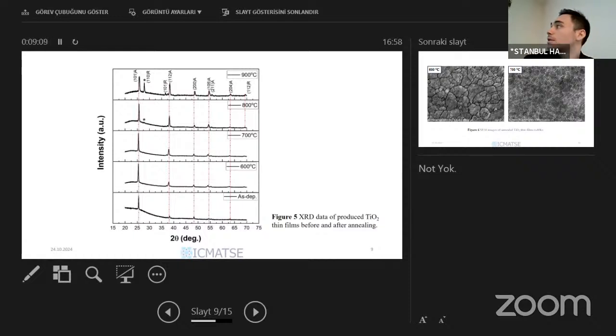Looking at the other temperatures, 600 and 700 also continue the anatase phase. At 800 degrees there is a small feature marked with a star, which is the rutile phase, but it's not a real peak, just a little indication. At 900 degrees, which has a milky structure as shown in the previous slide, we have a rutile phase near the anatase phase. So we can obtain a phase transformation from anatase to rutile, but we should see both phases in the same graph, the same chart.